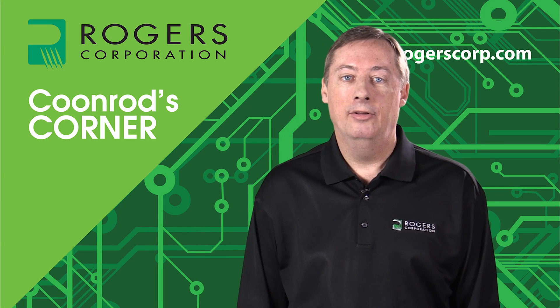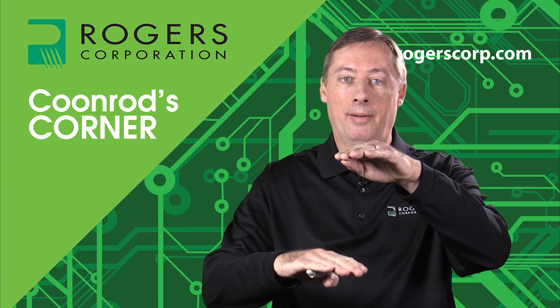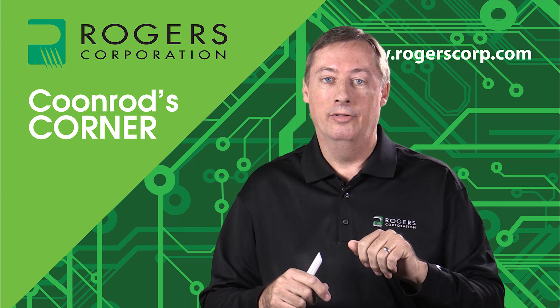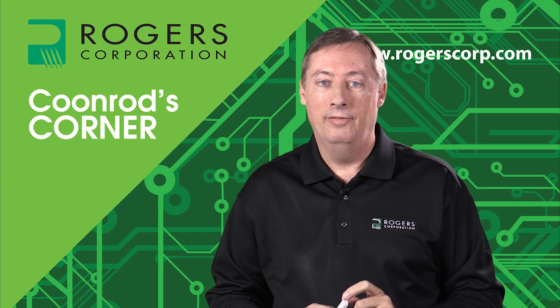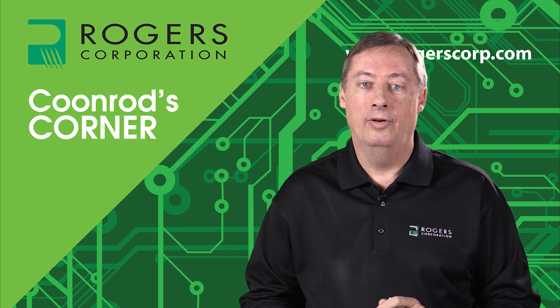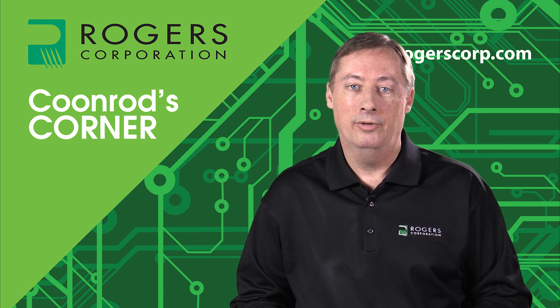A common question is why final plated finishes impact insertion loss, especially in the case of microstrip. A microstrip transmission line is a two copper layer circuit with a signal plane on top and ground plane on the bottom. Most of the electric fields are between the signal plane and the ground plane, and the plated finish cannot affect those interfaces. The plated finish actually affects the three edges of the signal conductor itself. At the corners, there is high current density and high electric field intensity, so for ENIG it is really a corner effect — the difference in conductivity at the corners — that makes a difference for a microstrip transmission line.